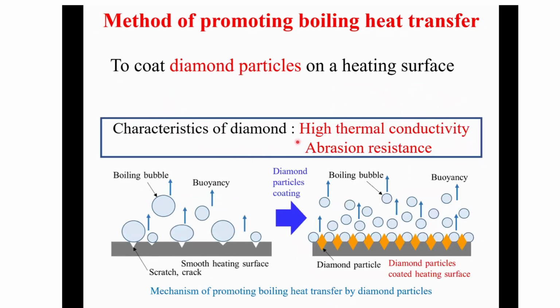So now I implement the diamond coating, that is, the coated diamond particles on the heating surface. We know that the characteristic of diamond is high thermal conductivity. On the left side, as mentioned previously, is the smooth surface, but there are many small dimples. This promotes the bubble. On the right side, the very small particle. This is a diamond, also micro size. This particle is installed on the surface. There may be artificial dimples like this. And the diamond has high thermal conductivity, so the bubbling is promoted with increasing time.